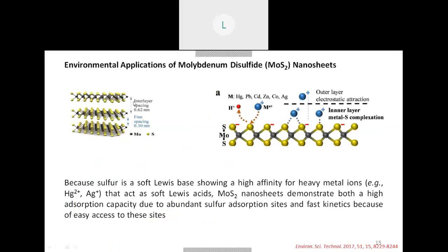This is one more advancement in the layered structure. After graphene, molybdenum sulfide was very famous for its surface area and the functionalization over the surface. You find this is the structure of MoS2, which has an interlayer space of 0.62 and a free space of 0.3 nanometers. So these surfaces have very low covalent or low van der Waals attraction in between. When you go for ultrasonication, these layers can be separated from each other, and then you get monolayers. These monolayers have a huge surface area for removal of any type of pollutants which is cationic.